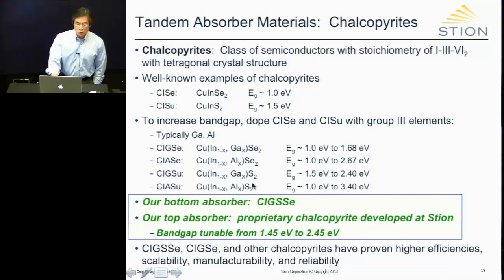Right? One way to do this is to dope it with other group 3 elements to replace some of the indium to increase the band gap. And the typical ones people dope this with are gallium and aluminum. So if you look at copper indium diselenide and you dope it with gallium and aluminum, you get this structure here, and the band gap changes from 1 to 1.68, or in the case of aluminum, 1 to 2.67.